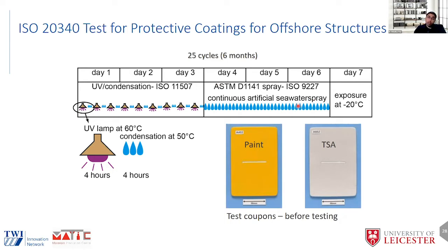Instead of using sodium chloride solution, which ISO 9227 suggests, we used synthetic seawater, ASTM D1141, to actually replicate the chemistry that is there in seawater. And on the 7th day, we exposed the samples to -20 degrees. And we repeated this cycle 25 times, which took about 6 months for completion.